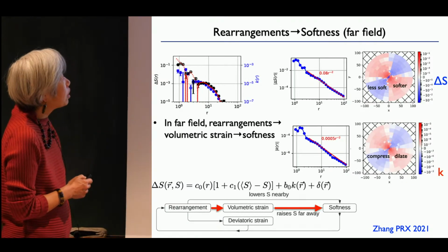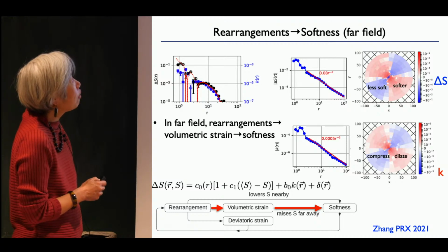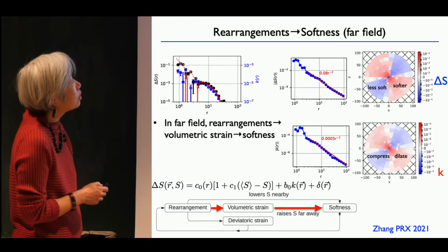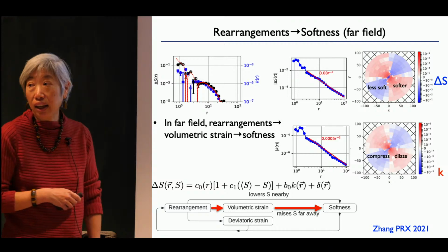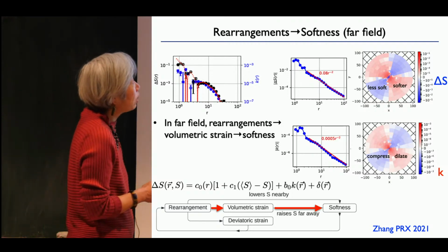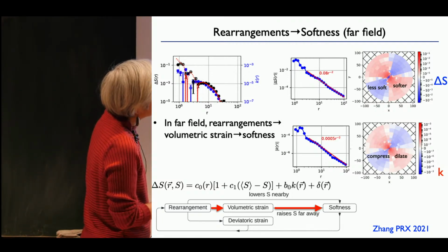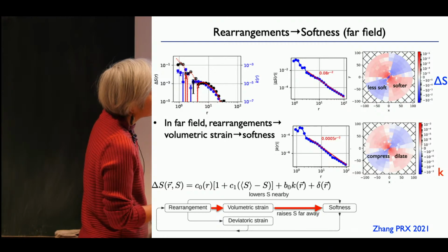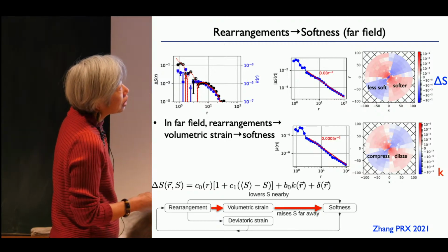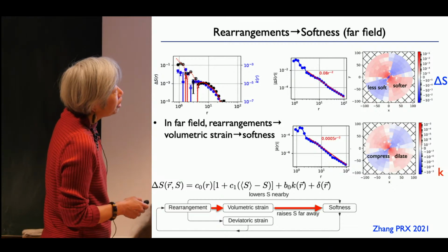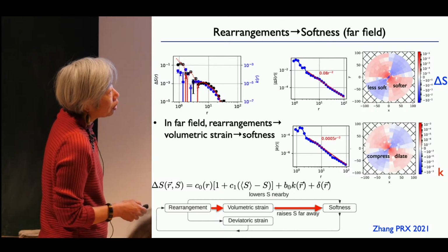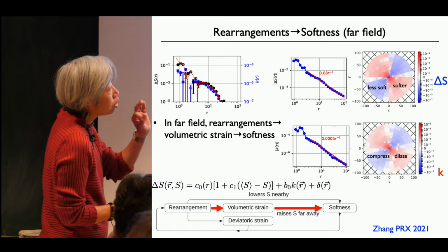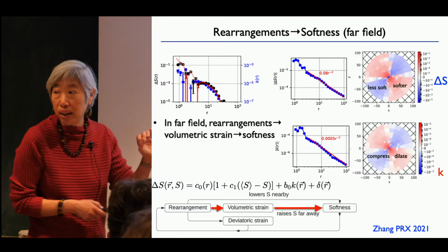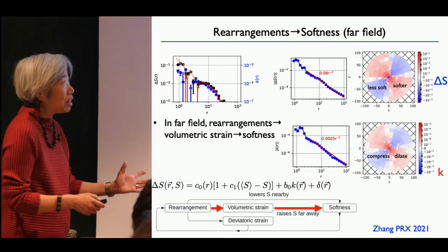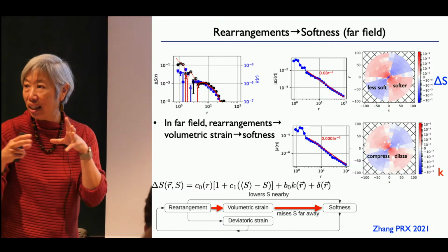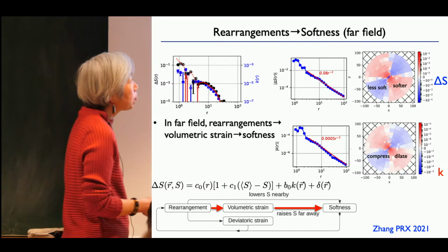So here's the change of softness as a function of distance. What you see in the far field is that it follows the volumetric strain. Okay, it looks exactly like the volumetric strain. And in fact, it has this 1 over r squared tail. And if you look at the angular dependence, it looks like this, where blue is less soft, red is softer. And indeed, if you look at the volumetric strain, that's where the system is locally dilated, and here's where it's locally compressed. Okay, and that makes perfect sense. Changing the density makes a big difference to softness.